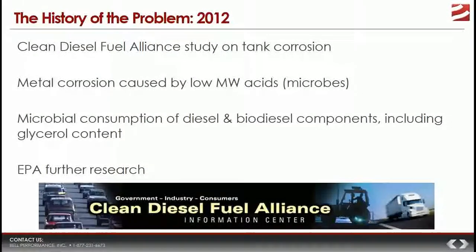Low molecular weight acids are basically lightweight acids like acetic acid, which is vinegar, like formic acid, ones like that. And they were speculating that the corrosion was being caused by these light acids that they found in these systems, and that these light acids didn't just magically appear. They were in there because they had been produced as the metabolic byproducts of microbes in those tanks.